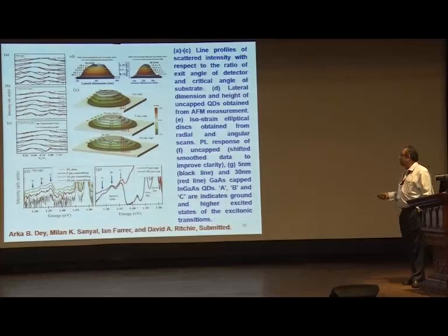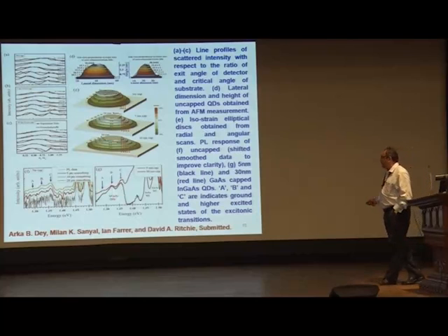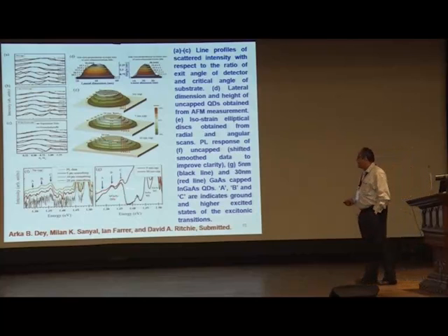variation and this kind of plot from a single quantum dot, and this is the kind of PL which comes when it is uncapped. The moment you do the capping, of course, the PL intensity goes up, but what we found is that the position of these peaks is more or less independent of this capping, and that makes our life simple.